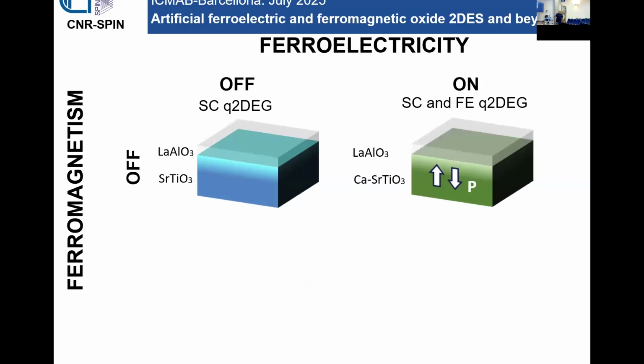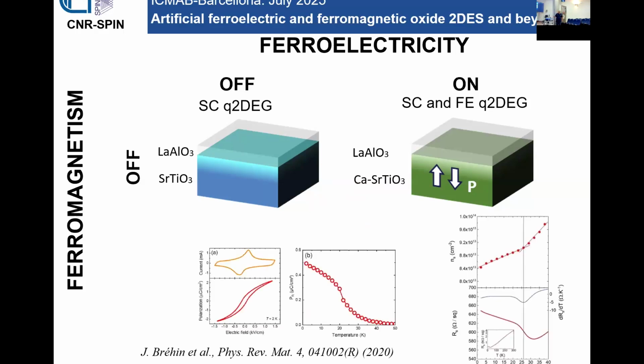To introduce ferroelectricity, some colleagues have proposed another approach, essentially depositing lanthanum aluminate on bulk calcium-doped strontium titanate. With 1%, 2% of calcium doping, the bulk strontium titanate becomes ferroelectric. And by doing so, you can grow lanthanum aluminate or other oxides, like aluminum oxide, and you can get a 2DEG which is essentially ferroelectric. I mean, it shows a coupling between ferroelectricity and the transport properties. That's to be more precise.